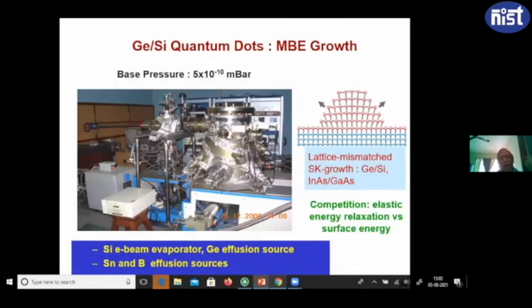And probably I have not shown you how typically this is grown. This is a very, very sophisticated technology, how these germanium quantum dots can be grown on silicon or silicon dioxide. This is basically ultra high vacuum equipment. As you know, the base pressure of the system is about 5 × 10⁻¹⁰ millibar.